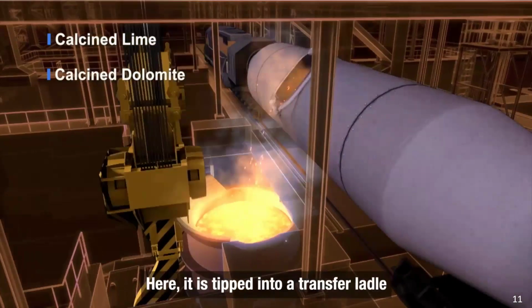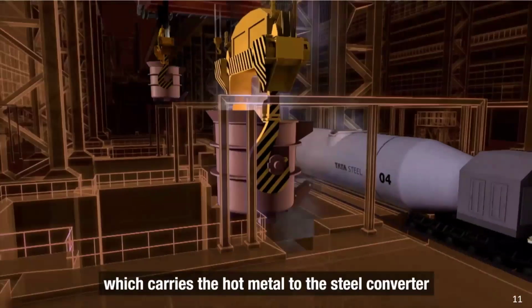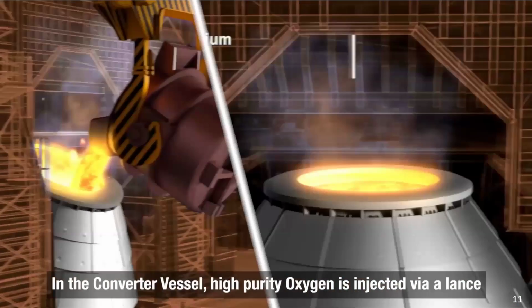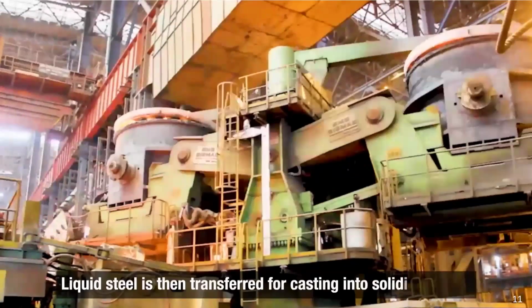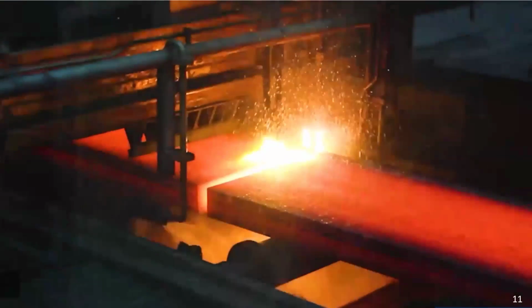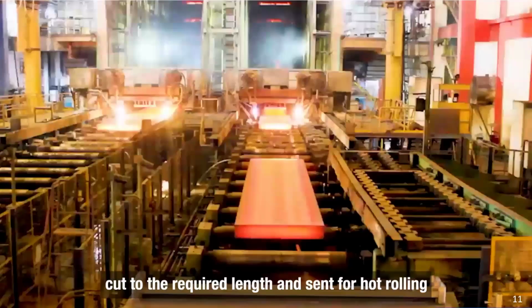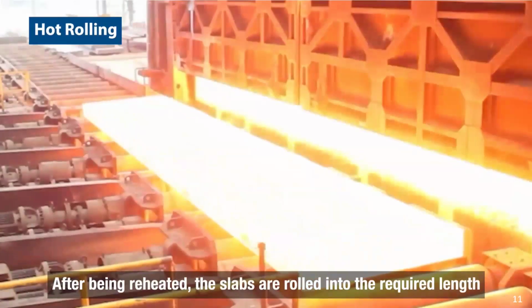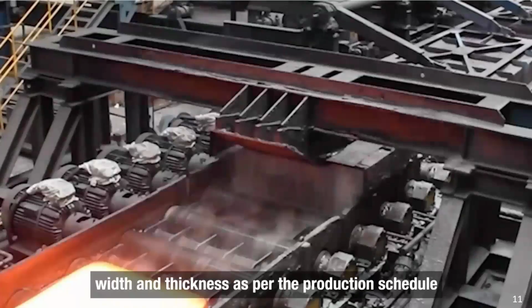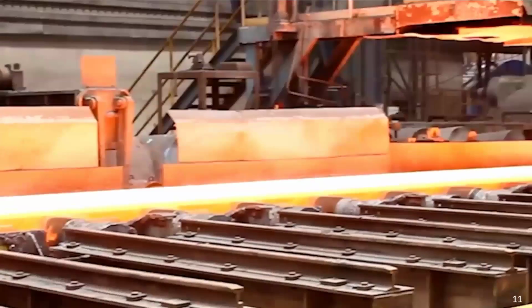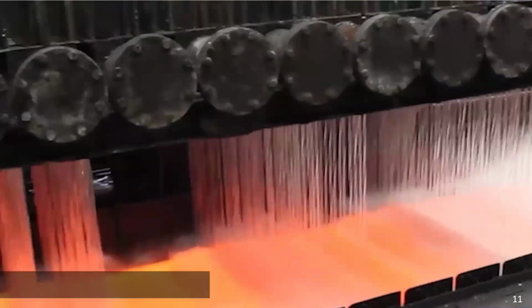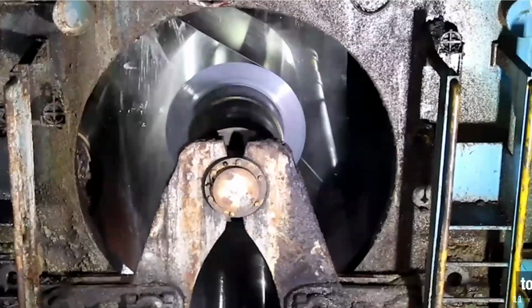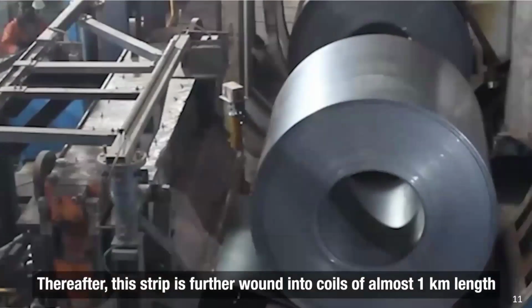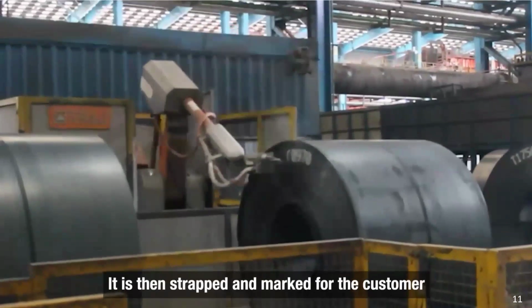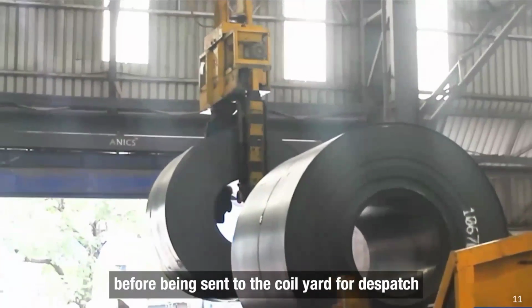Here, it is tipped into a transfer ladle, which carries the hot metal to the steel converter. In the converter vessel, high-purity oxygen is injected via a lance to refine the hot metal into steel. Liquid steel is then transferred for casting into solidified slabs, cut to the required length and sent for hot rolling. After being reheated, the slabs are rolled into the required length, width and thickness as per the production schedule. The hot rolled strip is then passed under laminar cooling to achieve the desired mechanical properties. Thereafter, this strip is further wound into coils of almost 1 kilometer length. It is then strapped and marked for the customer before being sent to the coil yard for dispatch.